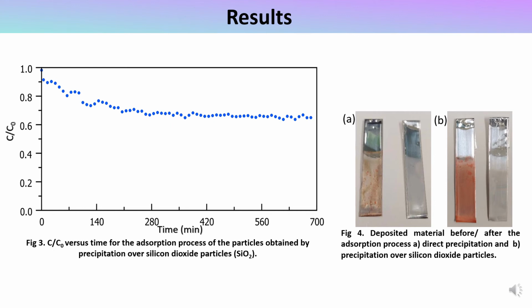In figure 3, we observe the graph of concentration versus time for the adsorption process of the particles obtained by precipitation over silicon dioxide particles. In it, we observed that the material adsorbed 35%. The pictures in figure 4 correspond to the plates of deposited material before and after the adsorption process. The letter A corresponds to direct precipitation and the letter B corresponding to precipitation over silicon dioxide particles. This result suggests that the boehmite on silicon dioxide particles can be successfully applied for environmental applications.